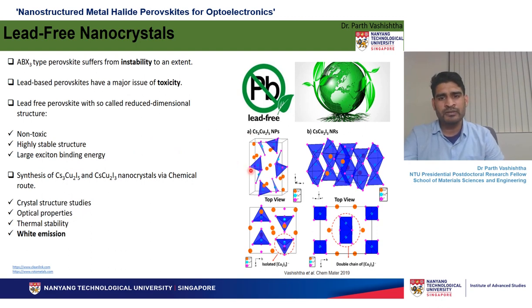High exciton binding energy gives a higher photoluminescence quantum yield and makes it extremely stable. So this material was stable in air for months, actually. The photoluminescence efficiency was much more stable. And we made these two types of structure, which I'll talk about in more detail. Both are iodide based materials, but the Cs3Cu2I5 has zero-dimensional individual octahedra, no corner sharing. But the CsCu2I3 has a rod kind of, basically one-dimensional space.